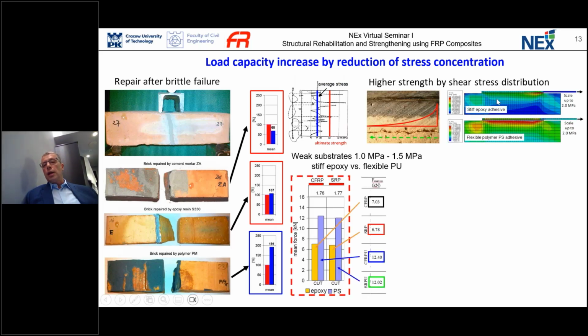If we consider the shear lap test, single shear test, you can see that if we bond the composite material to the weak substrate with stiff epoxy resin, we have stress concentration that, after initiation, the crack propagates through the whole bonding area. If we bond the structure with flexible material, we redistribute the stress more evenly, so we reduce this peak of stress concentration, we can protect the weak substrate, and also increase the ultimate force.